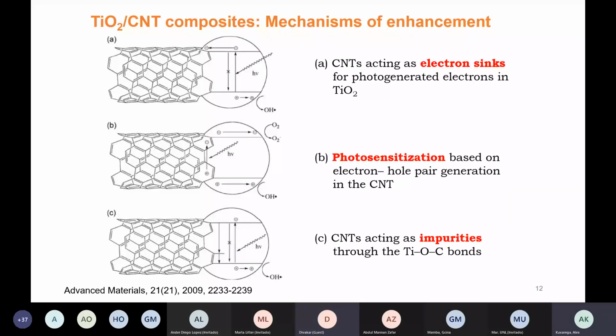So this slide is showing some of the mechanisms of the enhancement of the photo efficiency when we have a combination of a semiconductor, probably TiO2, and carbon nanotubes, where the carbon nanotubes can act as electron sinks for the photogenerated electrons. Then they can act as photosensitizers because they are very good absorption materials in the entire UV region. And they can also act as impurities through the formation of Ti-O-C bonds. In that process, you form intra-band gap states where you have a reduction in the band gap of the semiconductor. So they play quite a significant number of roles in enhancing the photodegradation of the pollutants.